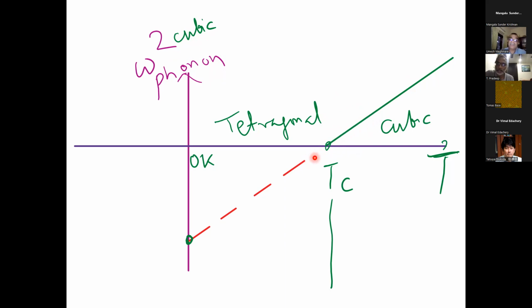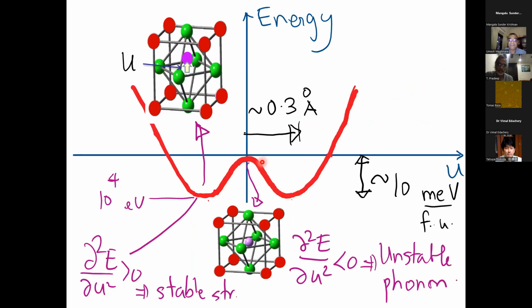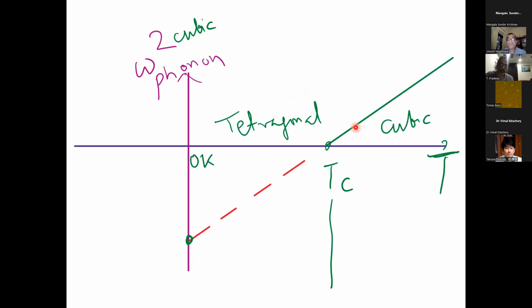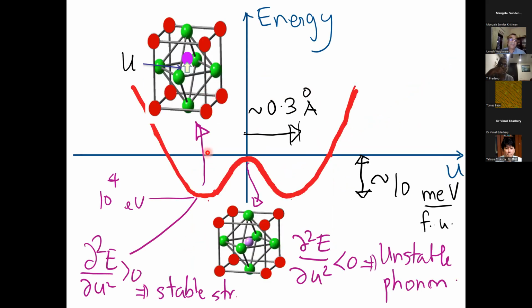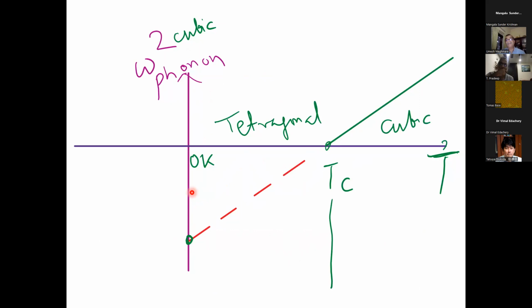And as you lower the temperature, the cubic phase cannot be stable, because this phonon frequency squared would have become negative, and you get a local maximum of energy. And this is the frequency that I showed you on the last slide is negative. Okay, this one. So this is how it looks. But in the real world, below TC, the material stabilizes in the tetragonal phase, and in fact, this phonon splits and becomes two hard, or stable, phonons in the tetragonal phase, and that's reflected in the second derivative being positive for the tetragonal phase.